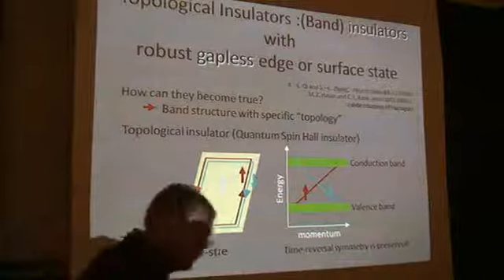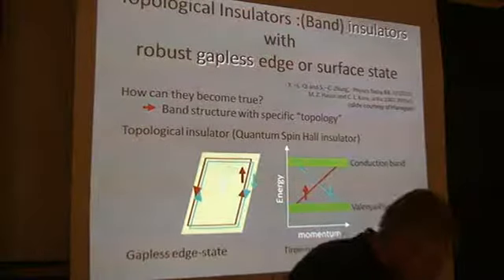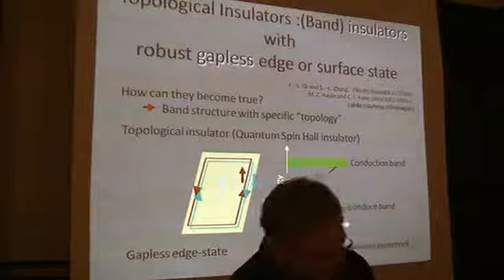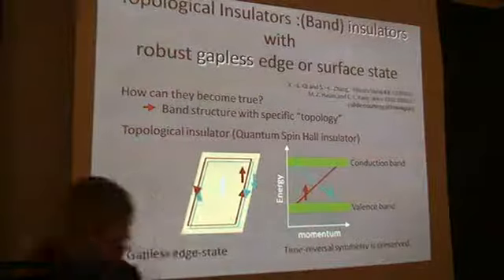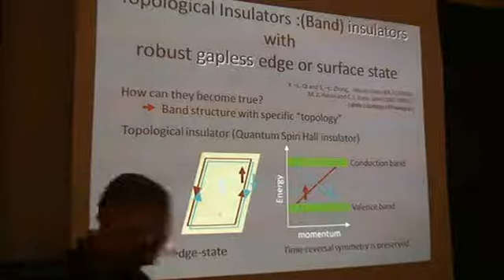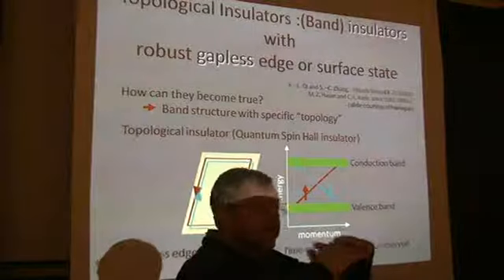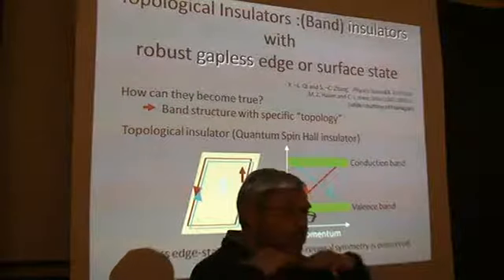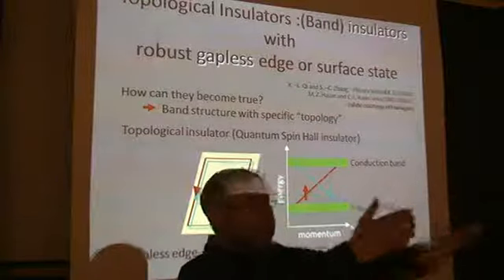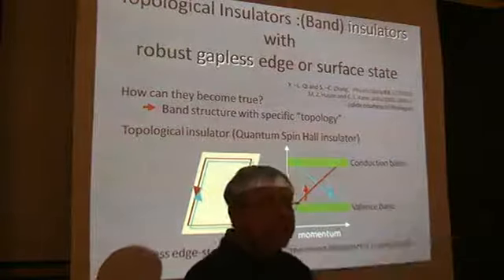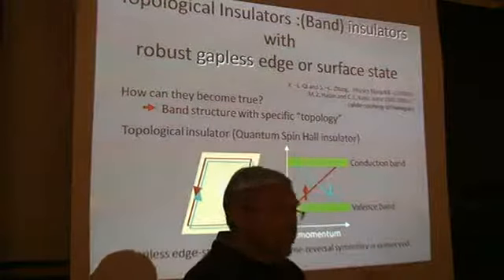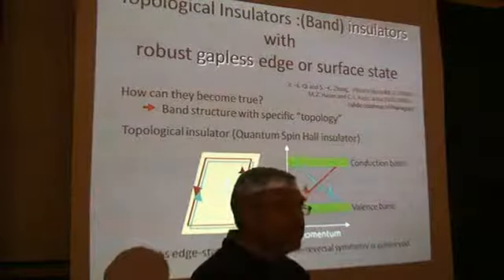Yeah, so let me qualify it, since you keep doing this. In a way, this is my concluding slide or pre-concluding slide. What's really going on? Of course, there are protected states, but what happens every time you put a strong impurity is that whatever the degeneracy of the sheet of two-dimensional protected state is, it jettisons one, lets it localize, and the current goes around it, and the rest of it, of course, does provide this e squared over h conductance. So I'm not arguing that the e squared over h and anti-localization and other things will not happen. I'm just arguing that something has to give, nevertheless. There has to be some spectral weight redistribution to provide these bright spots I showed you.